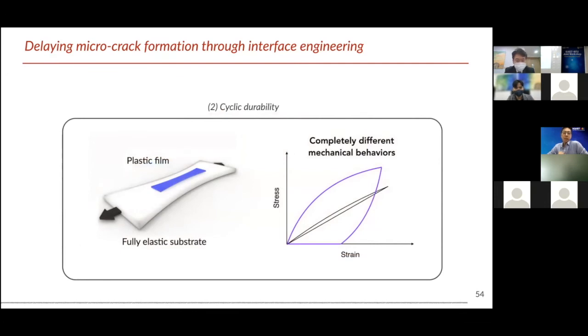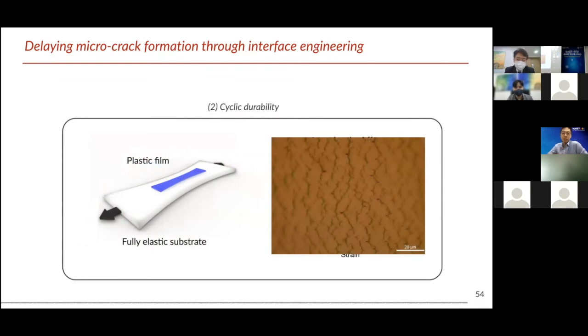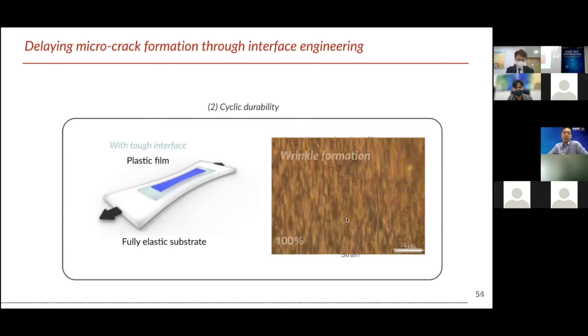And the second feature is the cyclic durability. If you have a plastic film as the semiconductor and the substrate is an elastomer, basically they have very different cycling mechanical behaviors. So during cyclic testing, we see instability. This is the first cycle. After 50 cycles at 100%, you can see the merging of many cracks, meaning that because of the difference in cycling mechanical behaviors, it affects their cyclic durability. However, our interface has adaptive properties, so it can compensate for the different residual strain by intrinsically forming this kind of wrinkle. Based on the wrinkle formation, they can stabilize the system, so we can improve the cyclic durability.